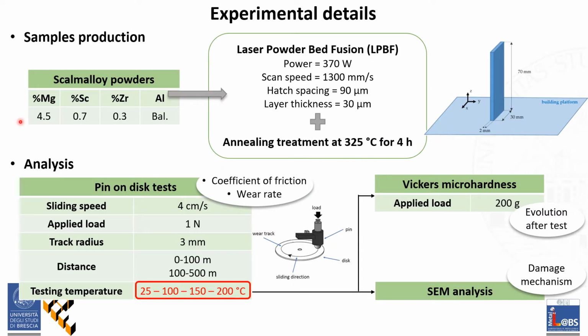To do this, samples were manufactured starting from Scalmalloy powder via laser powder bed fusion process, with the parameters reported in the central box and the shape reported on the right. Samples were annealed at 325 Celsius degrees for 4 hours. Then, pin-on-disc tests were carried out at 4 different temperatures: room temperature, 100, 150 and 200 Celsius degrees.